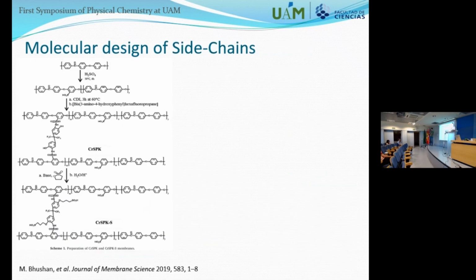Another possible strategy is to work with the molecular design of the side chains. So we have the backbones, and then we have some side chains pending from those backbones. We can work on the backbones as we saw, or there's also the possibility to work on the side chains. So in this work, well, sorry, you can see the work here, I think it's below the presentation. What they do is work with the side chains. They are trying to do the cross-linking of the polymer backbone, using this cross-linker.